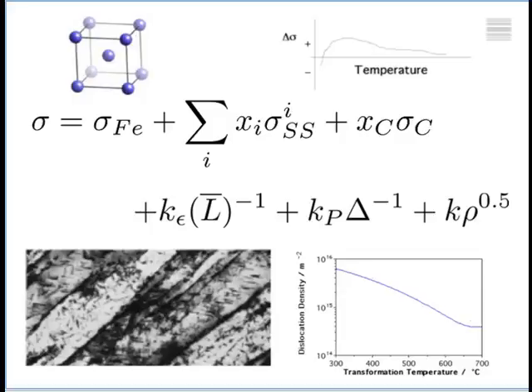Of course, we never use steels as pure materials. We add alloying elements, and those alloying elements will have different sizes of atoms, and therefore they also contribute to the strength of the steel. And that contribution will depend in some way on the concentration. So if I add 1 weight percent manganese, I might get an increase in strength of 70 megapascals. If I add 1 weight percent of carbon, I will get a much, much bigger increase in strength, because carbon sits in the holes between the atoms and it causes a lot of distortion inside the crystal structure. So it's a very powerful strengthening mechanism.